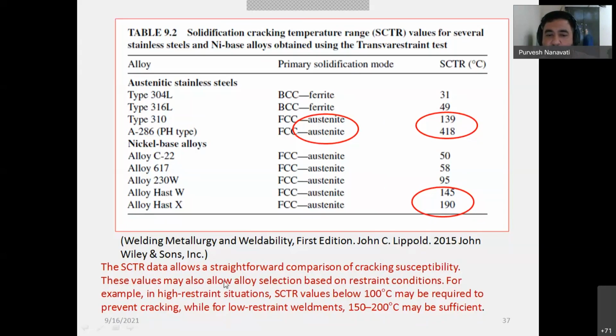So you read the below line. The SCTR data allows a straightforward comparison of cracking susceptibility. This value may also allow alloy selection based on the restraint condition. Now you could choose the alloy depending on these guidelines, right? Now, if your restraint is very high, then you always go for 304, 316L and you will not go for 310.